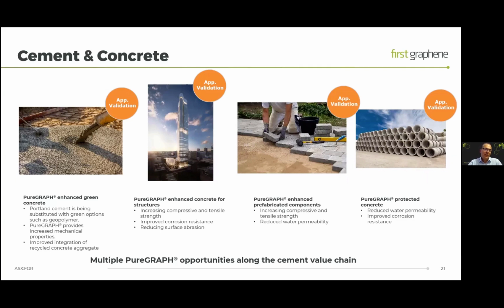For cement manufacturers, the industry is looking at many alternatives to ordinary Portland cement. These systems that are being used typically don't perform as well. So adding performance through additives to these cement products is quite significantly important. Graphene can potentially increase the strength of these systems and also improve the integration of some of these alternative aggregates. And as I mentioned, recycled concrete is one of those. In structures, obviously by adding PureGraph into concrete systems, increasing the compressive and tensile strength can have a significant impact on how structures are developed, designed, and constructed.